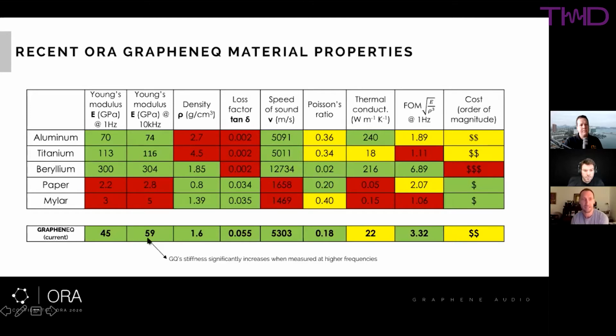So our material is currently not as stiff as aluminum in terms of its Young's modulus, but the density is much lower. When you look at a material, the speed of sound in the material really determines the frequency at which it will begin to break up, right? For a given dimensional loudspeaker, the wavelength that first fits within that dimension will start to create modes in the membrane itself and irregularities in the frequency response.